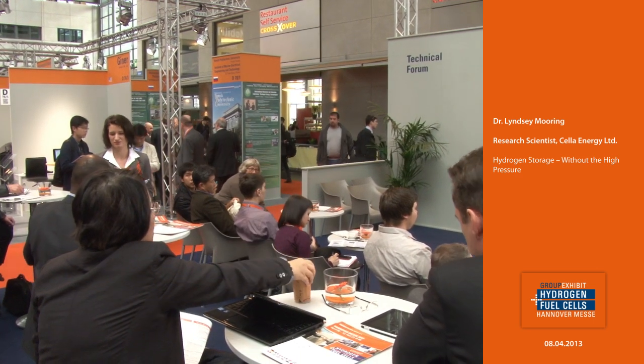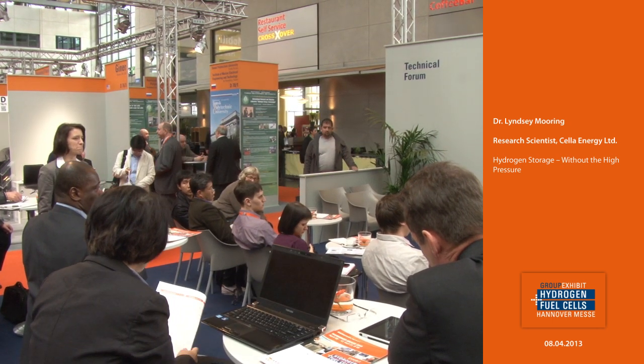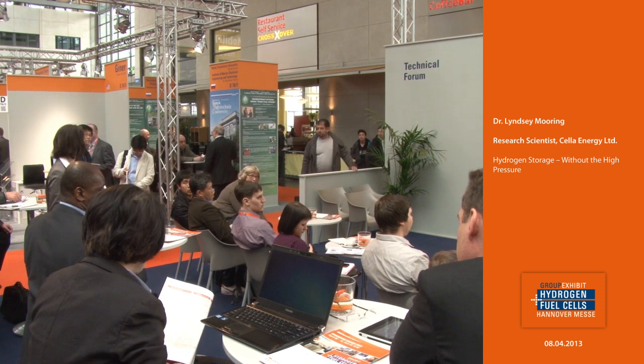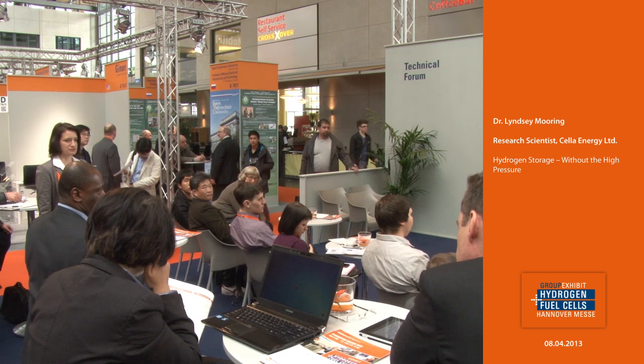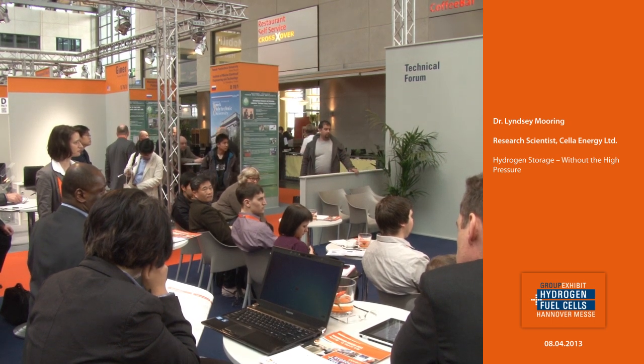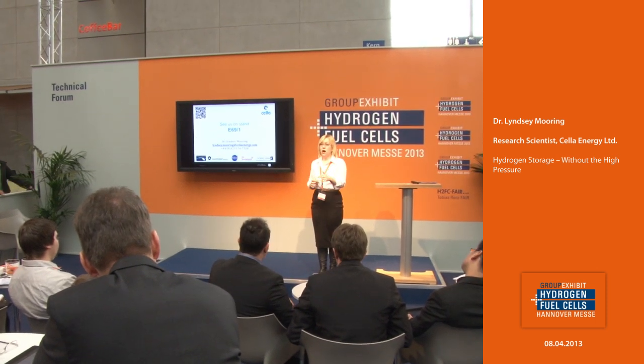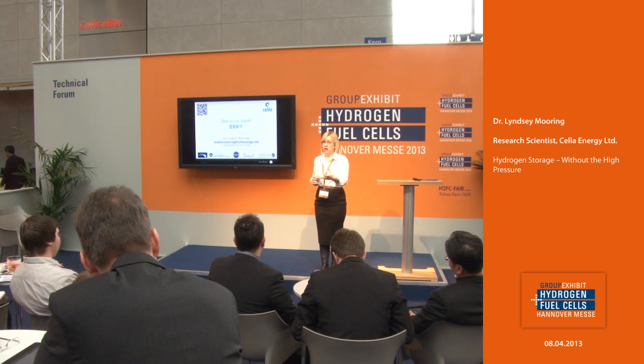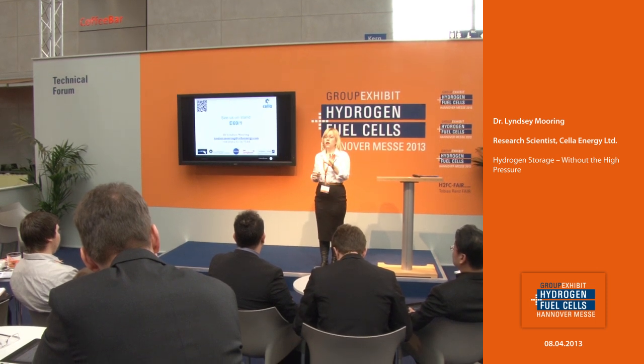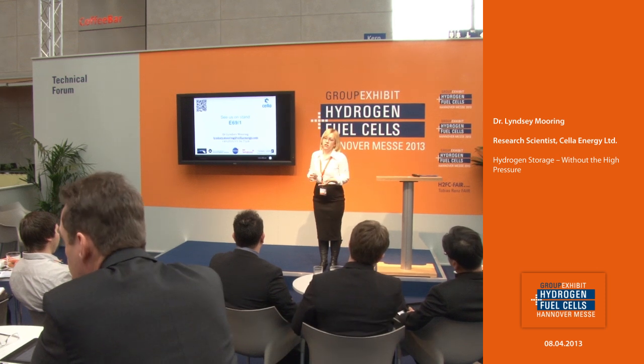Sure. The first one: you wanted this for transport applications, but you said one of your requirements was to have it at room temperature or ambient. For normal transport, you need temperatures from -40 to +40. Is that viable? We've already conducted storage tests going up to 60 degrees to check that the hydrogen won't be released, and I'm pleased to say that it's stable. The kinetics are so slow that you would consider it stable.